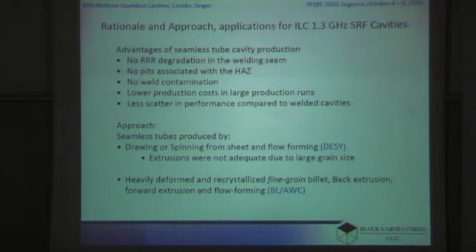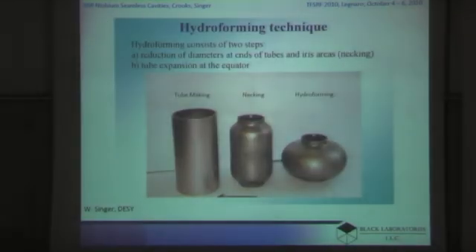One other issue is that in the deep drawing or the spinning method of tube from a flat material, the properties are directional because of the directional properties of the rolled material, and that causes a problem in hydroforming where you'd rather have axisymmetric properties. Our approach at Black Laboratories and working with ATI Wah Chang was to produce a fine-grained billet initially by heavy working of the billet and recrystallize it and use that as a feedstock for an extrusion process. For both of these processes, the tubes were produced and necked by spinning at DESY to produce the iris regions of the cavity, and then expanded by hydroforming.